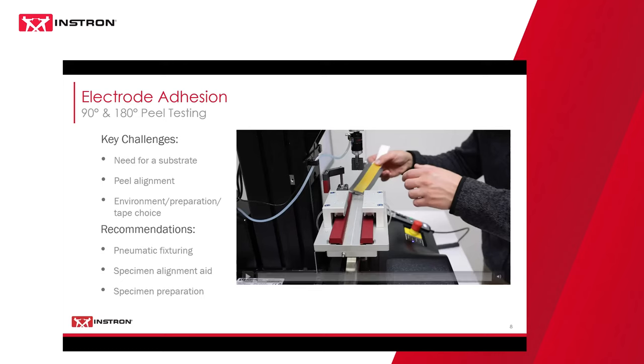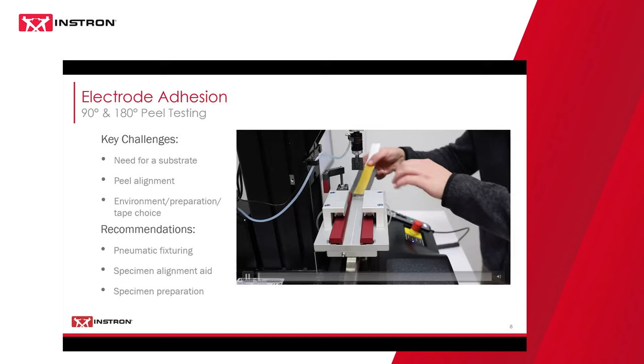The fixturing shown to the right here is an example of Instron's pneumatic 90-degree peel fixture. This was designed specifically for electrode adhesion testing. So this fixture is an example of something that could be used. It incorporates pneumatic clamping of the specimen, so it makes it easy to grip the specimen down without a substrate. And then it uses what we call a swing clamp alignment aid that ensures a 90-degree start at each test. So I'll play the video here and show.